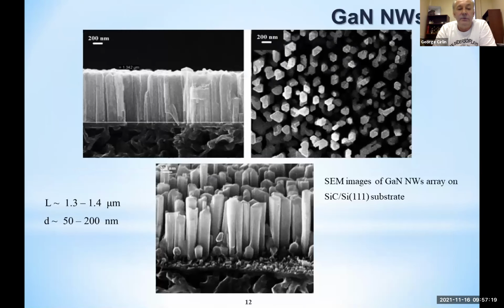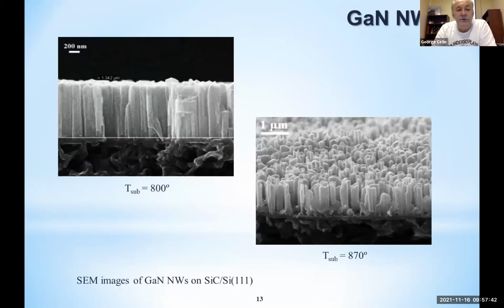And we started growing these gallium nitride nanowires on these kinds of structures, and it appears that it's possible. So this is how these nanowires look. Here is a thin layer of silicon carbide, these pores, and on top of them the nanowires can be grown. Different temperatures lead to different morphologies of the nanowires, so we can control in some predictable way their density and height.